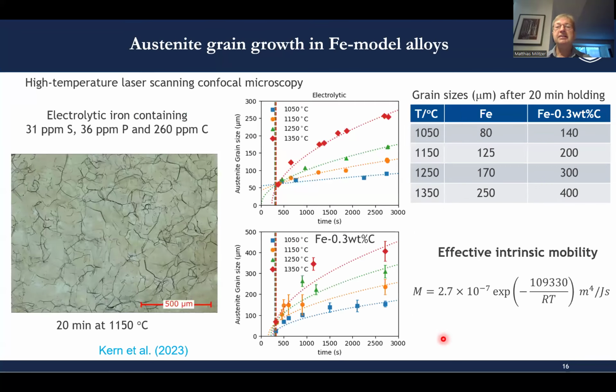So we have recently engaged in collaboration with colleagues in Austria at the University of Leoben, Kern and co-workers, looking at austenite grain growth in iron model alloys, where it surfaced that residuals can be very important. What they do is in situ measurement of austenite grain growth using high temperature laser scanning confocal microscopy, so a typical microstructure is shown here.